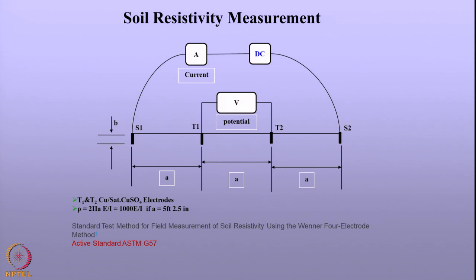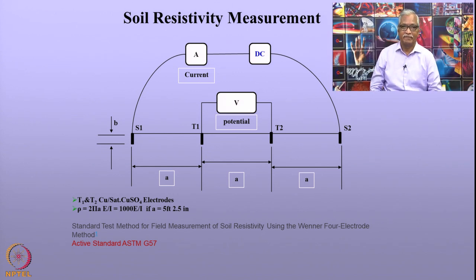So, let us now discuss how to measure the soil resistivity in the field. One of the most important techniques is the 4-point probe technique, and this is of course well known to material scientists. In this case, we use 4 pins which are inserted in the ground at an equal distance, and between the external pins a current is passed using a DC source. A known current is passed through these pins. Now, the inner 2 pins, which are kept at equal distance, measure the potential, simply using Ohm's law.